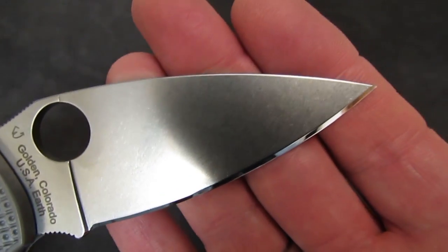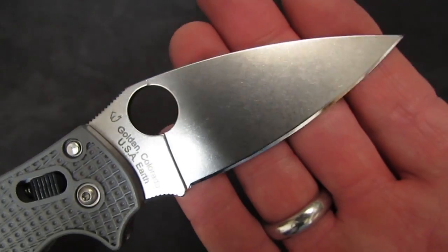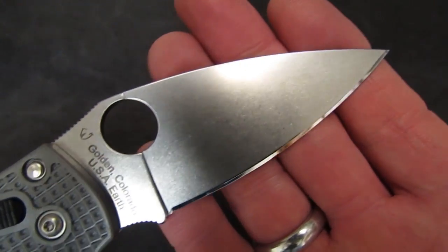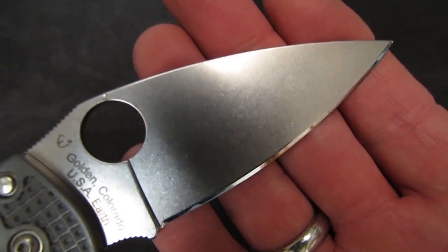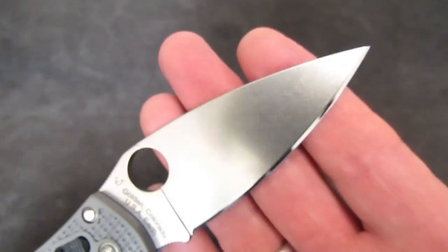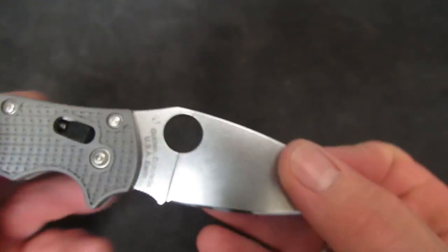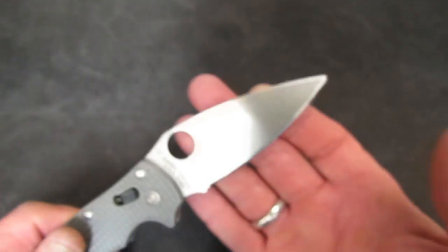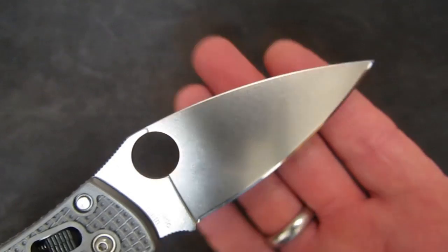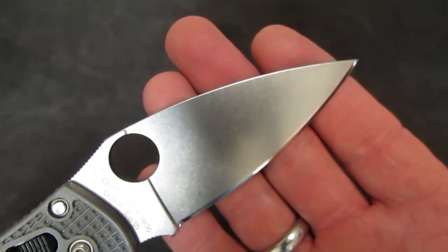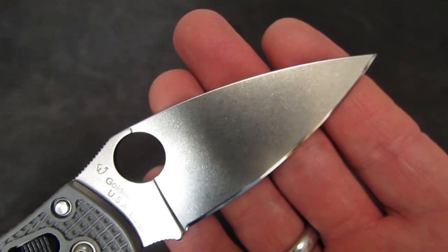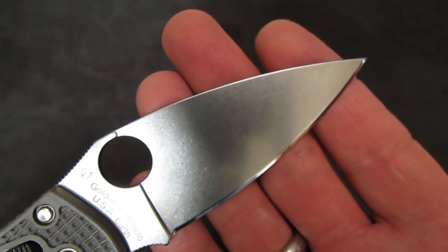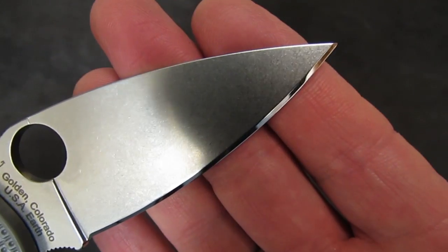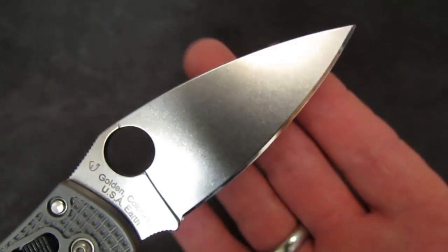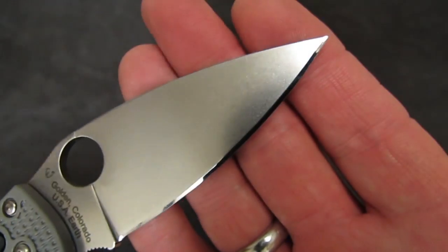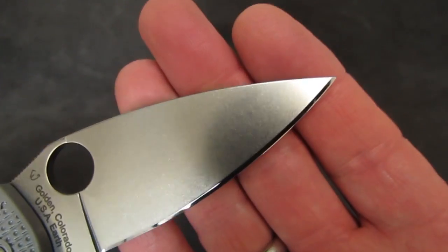Again, starting with 600 grit. You can imagine how long it took to take probably a 150 or 180 grit Spyderco factory finish to a near mirror polish, starting with a 600 grit stone. It took a long time. Why do I start with such a high grit? Well, I think of Maxamet as basically a ceramic that looks like steel. 6% vanadium, 10% tungsten, bunch of cobalt, and 2.15% carbon. There's barely any compliant ferrous metal holding all those brittle structures together.